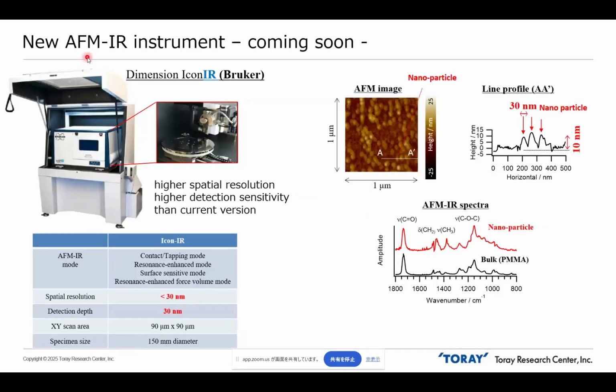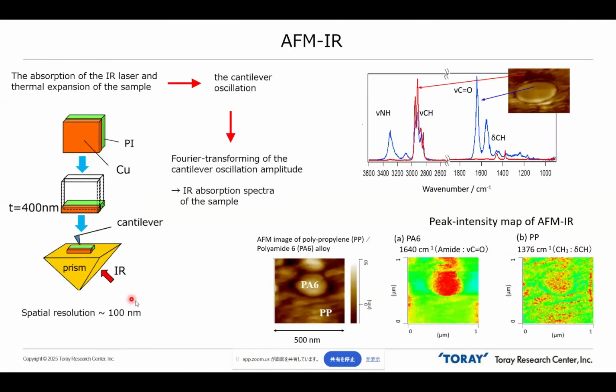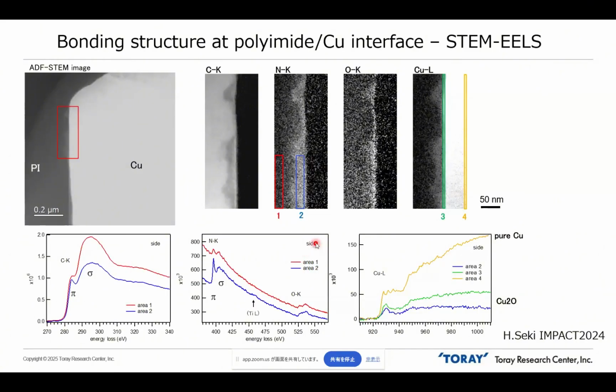Then finally, let me introduce our new experimental system regarding AFM-IR. In the current system, the spatial resolution is around 100 nanometers. So with this spatial resolution, it was difficult to detect this interfacial layer because the thickness of this interfacial layer is around 50 nanometers. It can be detected by EELS, but it was difficult to detect by our conventional AFM-IR techniques.